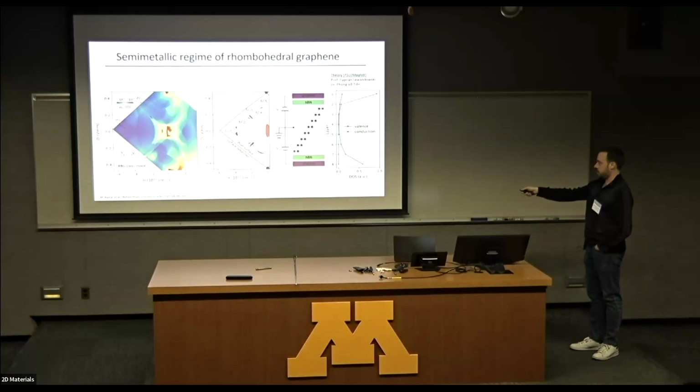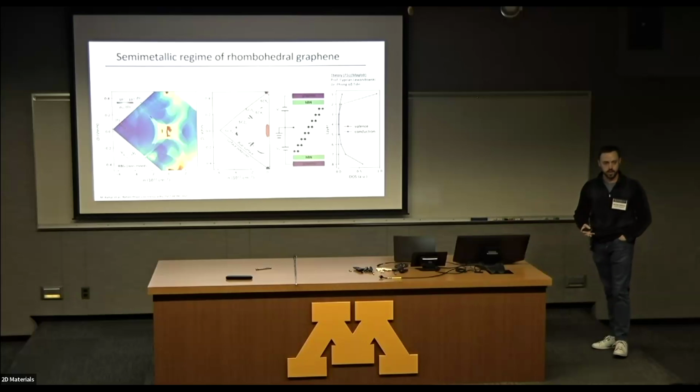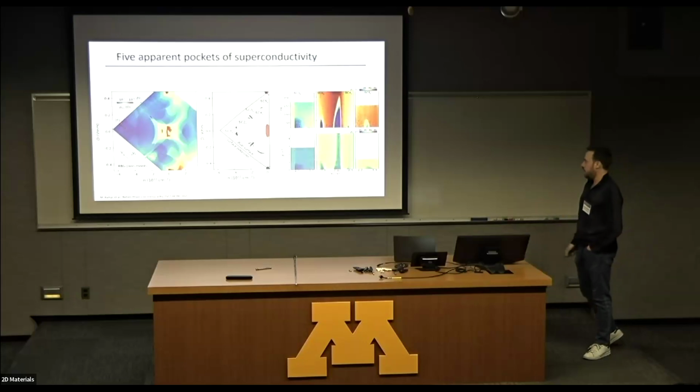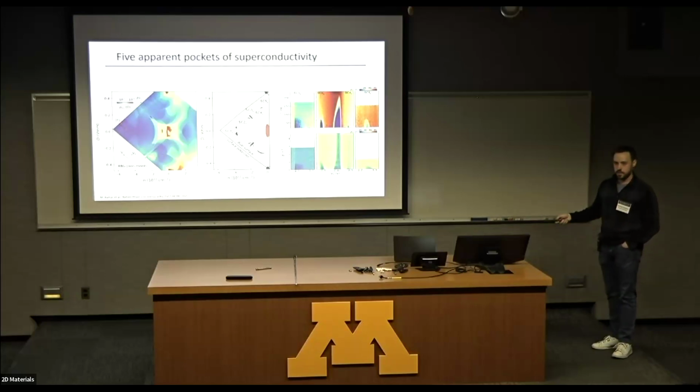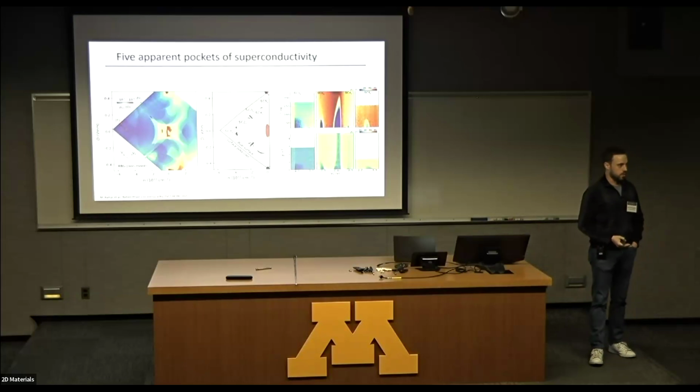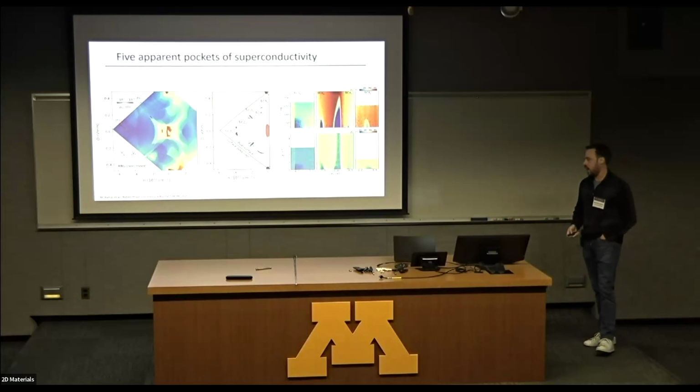But the interesting finding was that this dual surface regime is littered with small pockets of sharply suppressed resistance that looks like 2D superconductivity. And so the way that we can characterize that in transport is to measure resistance as a function of gate voltage in either temperature or magnetic field, and see these characteristic domes in temperature or field where the resistance is sharply suppressed from the normal state below a critical temperature or critical out-of-plane field.